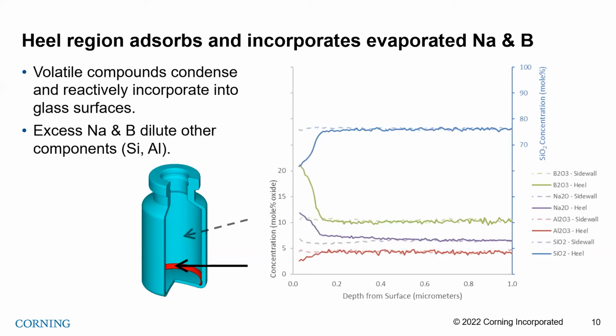Next slide, please. And so we can use tools like dynamic SIMS, secondary ion mass spectroscopy, to look at how that surface chemistry is altered. So the solid lines here show that region of the heel where sodium and boron, the purple and the green lines here, have been greatly enriched in the outermost, say, 100 nanometers or 150 nanometers of surface. That's like 1,000th the width of a human hair. And it's that enrichment that causes those flakes that I showed in the previous slide.